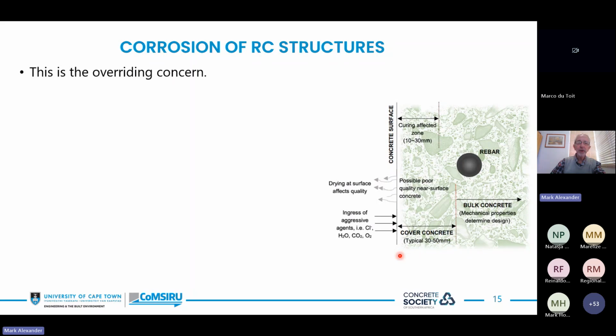Now, it's actually corrosion of the reinforced concrete structures that is the overriding concern. If we look at that diagram on the right, it's a well-known diagram where we see that we have rebar covered by the covercrete, and on the outside of the concrete structure, we have drying, certainly in the early stages after construction, and loss of moisture. We have a curing affected zone, which is relatively small. And then we get right from the beginning the ingress of aggressive agents, whether it's chlorides, water, carbon dioxide, or oxygen. And that cover concrete, which is typically 30 millimeters or maybe 50 at the most, is what protects that structure for its entire design life against corrosion. So we're not concerned about the bulk concrete, we're concerned about the cover concrete.